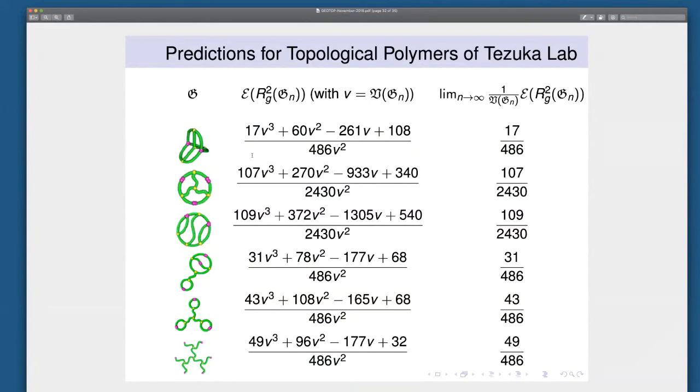So a big mystery for them actually was distinguishing between the ladder graph and the K33, because both of them have the pinks bonded in 2 groups of 3. And so, which one is it? One was bigger and one was smaller. And it turned out that this is the small one and the ladder graph is the big one.